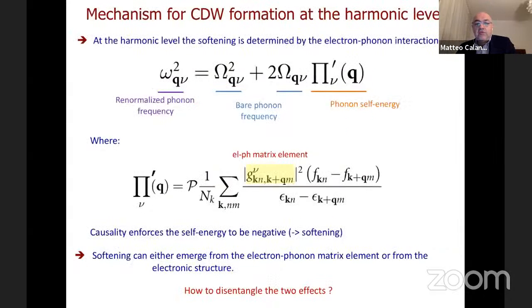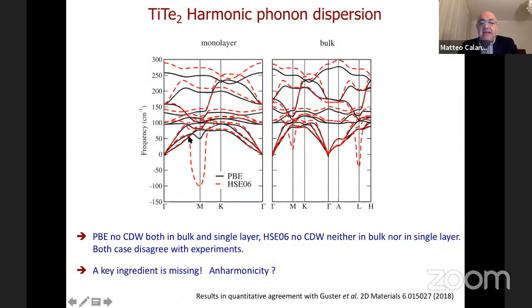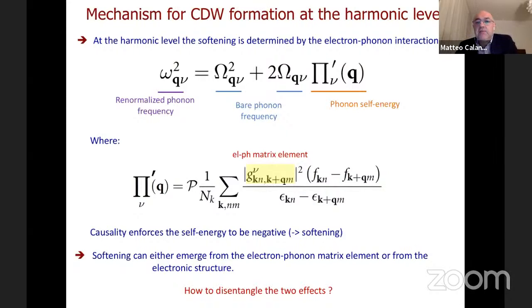But before going to anharmonicity, let me tell you what generates this kind of softening that you have seen also in titanium diselenide. The mechanism for charge density wave at the harmonic level is the following. At the harmonic level, the electron-phonon interaction is included in a typical linear response calculation, but also finite difference. And what you calculate is a renormalized phonon frequency, called small omega squared. This is the square of the renormalized phonon frequency, equal to a bare phonon frequency plus a correction that is due to the electron-phonon coupling.